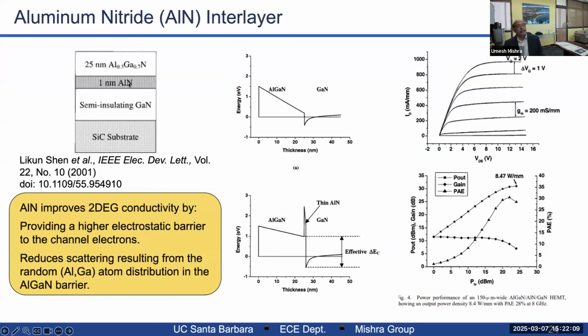We also did something I think was very clever. Normally, AlGaN GaN HEMTs have a band diagram like this. You just have AlGaN and GaN, and electrons are here. And electrons actually see the aluminum gallium nitride material. The aluminum gallium nitride material is an alloy, and so it actually scatters the electron through the process of alloy scattering. We introduced a 1 nanometer thick, thin aluminum nitride layer, which basically did 2 things. It separated the AlGaN from the GaN, but also, since aluminum nitride is polar, it has an inbuilt polarization dipole, you lift the conduction band.